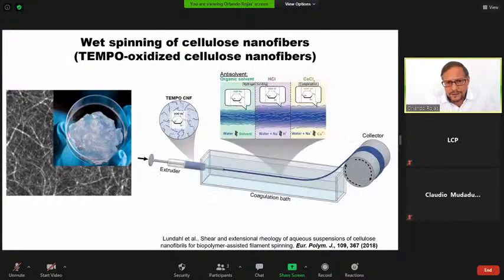Here I show more or less the same information, and I provide here in the bottom some references for you to check if you're interested. But my point here that I wanted to make is the fact that the anti-solvents that we use in the coagulation bath are simply water with HCl, with calcium chloride, or organic solvents, ethanol or acetone, and they really act very good as coagulants or anti-solvents for the nanocellulose dope to become a filament that can be spun out.